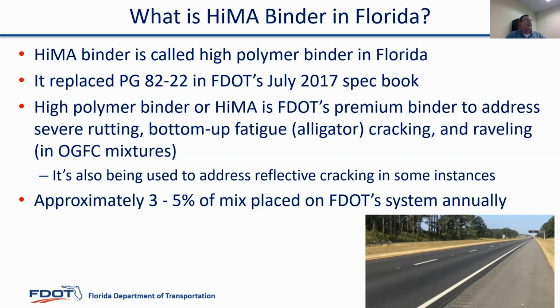It replaced the grade PG 82-22 in our spec books in July of 2017 after a couple of very successful pilot projects. And so what is it in Florida? High polymer binder, it's our premium binder to address severe rutting, bottom-up fatigue cracking, as Dr. Tim talked about earlier, and also raveling in open-graded friction course mixtures. And then more recently, we're also using it to address some reflective cracking where we can't mill out all the cracks.